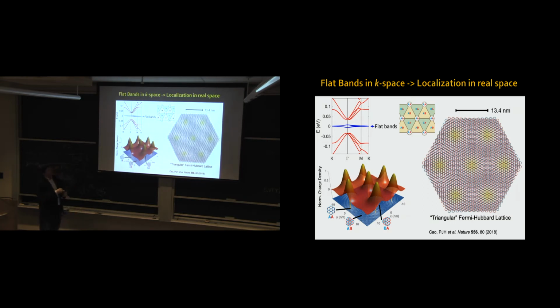And this is what's going to be my, in quotes, triangular Fermi-Hubbard lattice, on which I'm going to put electrons and look at the interactions. I say triangular in quotes because the AA sites form a triangular lattice - triangular means hexagons with a dot in the middle - but as you can see, the ABBA regions form a honeycomb plaquette. So it's actually a honeycomb lattice in reality. This actually took some time for the theorists to find out.